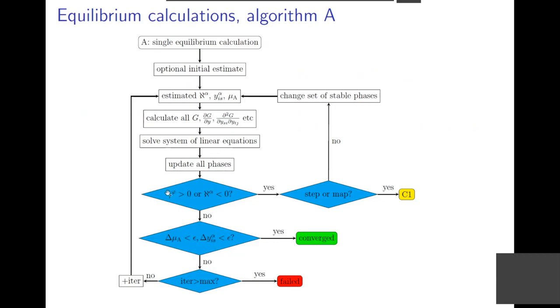And if an unstable phase wants to become stable, or a stable phase would like to disappear, you first check if you are doing a diagram, a step or map calculation. If you're not doing that, it means you update the set of stable phases and then you continue calculating here. If you're doing just a single equilibrium calculation, you check if the change in your chemical potentials between two iterations is smaller than a given value. If they are smaller than this value, you have converged. If they are larger, you make a new iteration and loop. And if you reach a maximum number of iterations and haven't converged, then the calculation fails. So this is the basic algorithm for the equilibrium calculation.